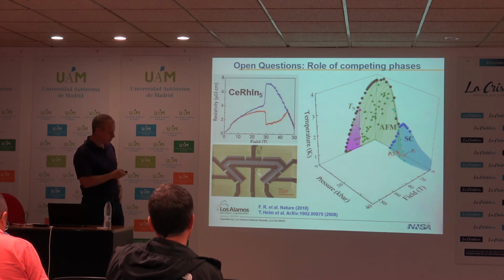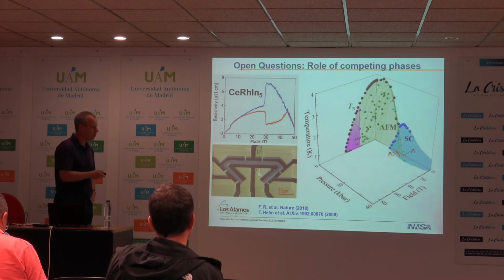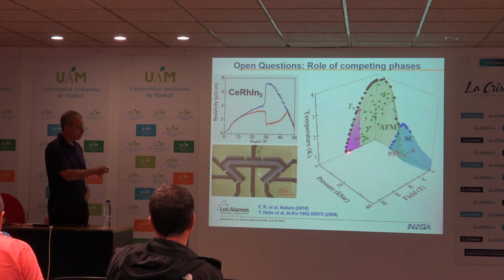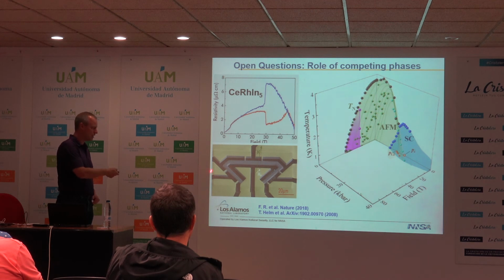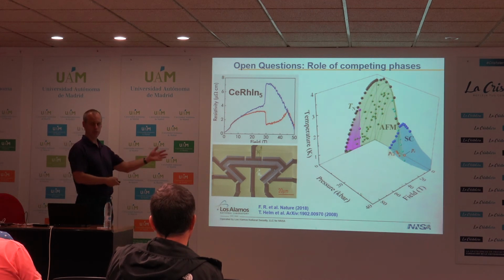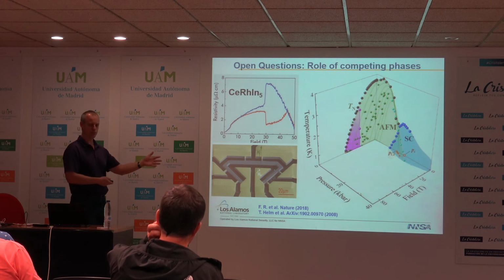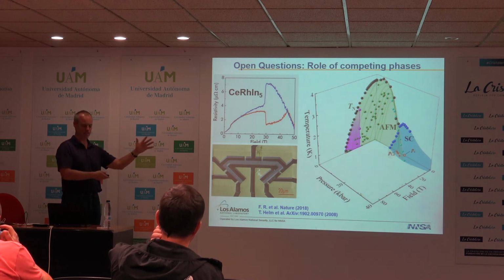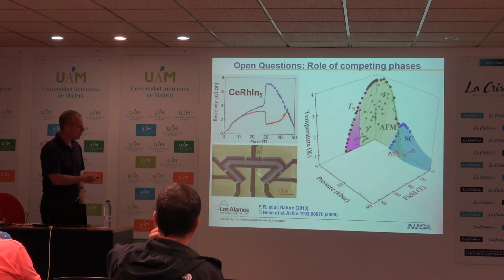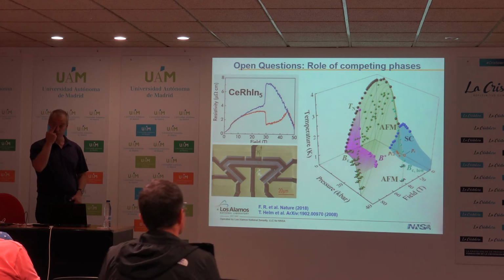And recent work, continued by Filip, is to actually try and do these measurements now as a function of pressure. So you're taking this FIB microstructure, putting it in a pressure cell, doing this in pulsed magnetic field. So experimentally, this is an incredibly challenging experiment. And here's a phase diagram that we found.